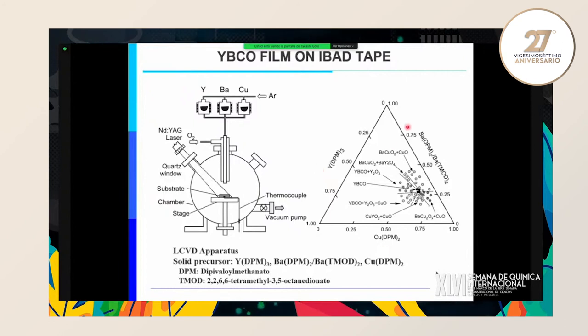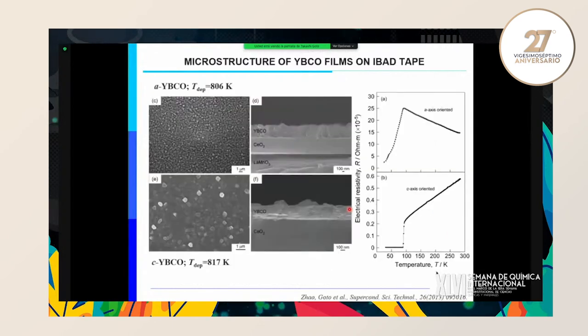By changing many conditions, we can find the condition to prepare YBCO film, because YBCO has many competing compounds, not only the 1, 2, 3 phase, but also yttria, cuprous oxide, and so on. It is a big effort, but we have to make it. And we can make A-axis oriented or C-axis oriented YBCO films, also with a mosaic structure, depending on deposition conditions.